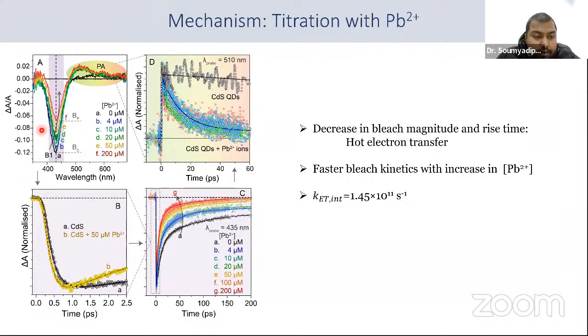Because of the hot electron transfer. What is hot electron transfer? In presence of lead 2+ ion, a subpopulation of the conduction band gets transferred to a trap state, which decreases the population at the conduction band. Now, when we have a depopulation of the conduction band, we have less signal in the bleach. This is not bleach recovery, but just a decrease in the intensity of the bleach signal.